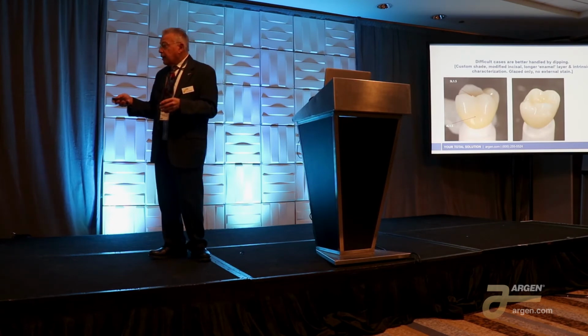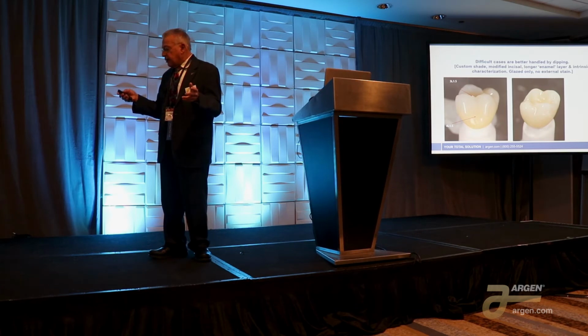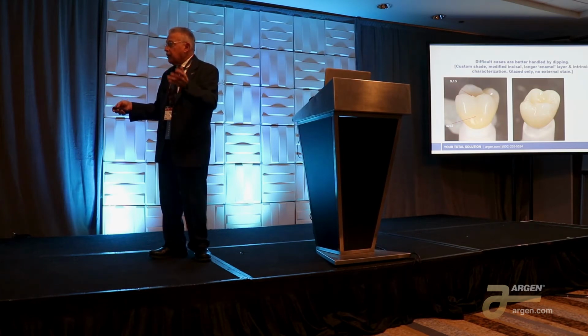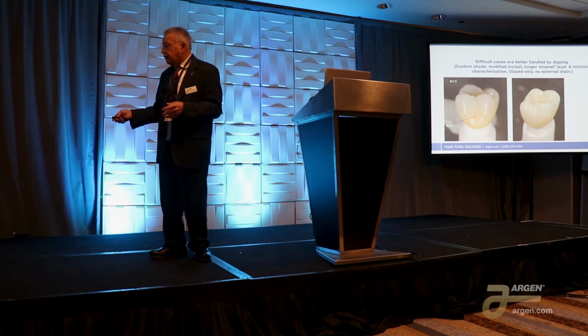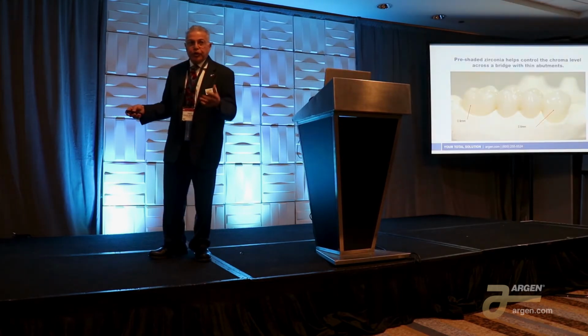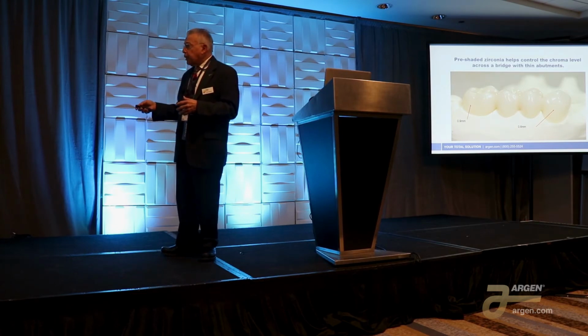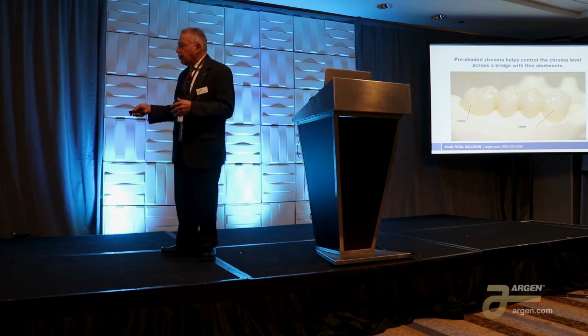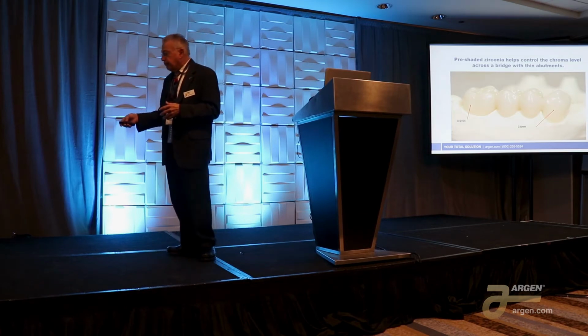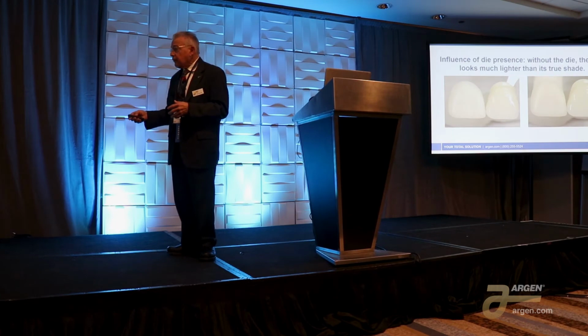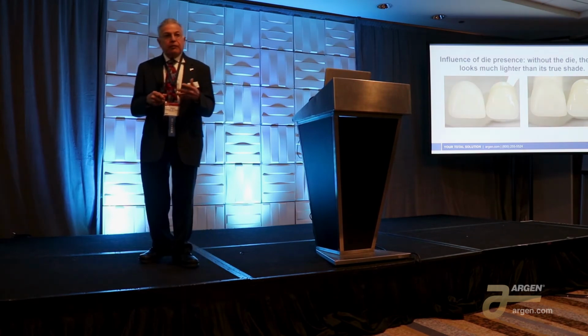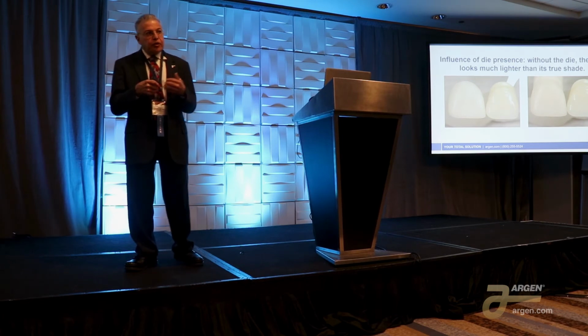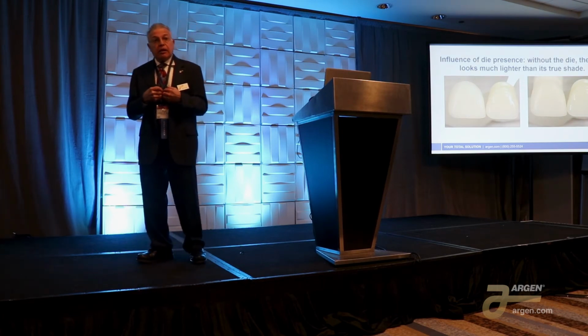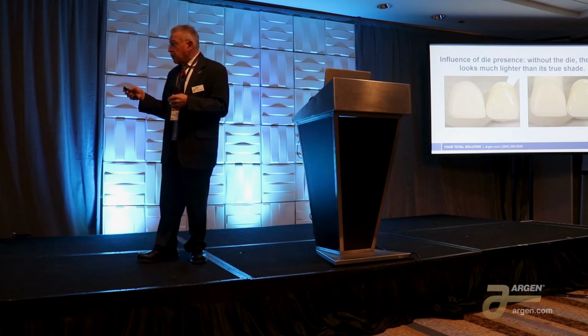So for dipping, you have a difficult case like this. It's best done by dipping and then doing your characterization. Here you have a case where the pre-shaded zirconia is best because you have a bridge and you're able to maintain the same chroma level independent of the thickness. So you're going from a thin abutment to a heavy pontic back to a thicker abutment, and the same shade. Also, when you're judging the zirconia, make sure you put it on the die, or else you're going to see a shade much lighter than it's supposed to be. And this is an example of that.